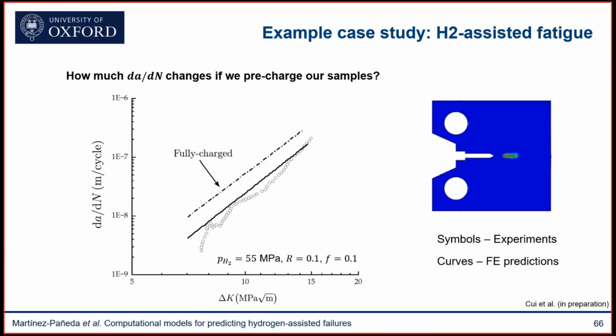So we see an increase of 2 to 5 times in the fatigue crack growth rates versus the data obtained in the absence of this pre-charging. And then, I don't know if 2 to 5 times is important or not. That is for the engineer to decide whether this increase in fatigue crack growth rate is important or not.